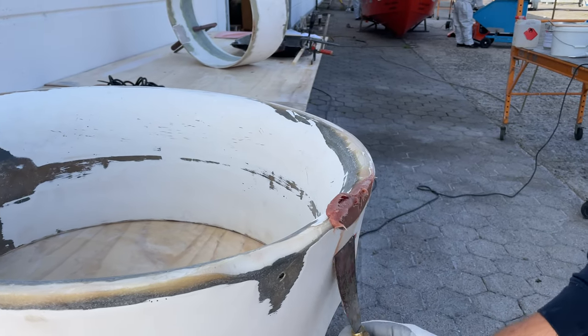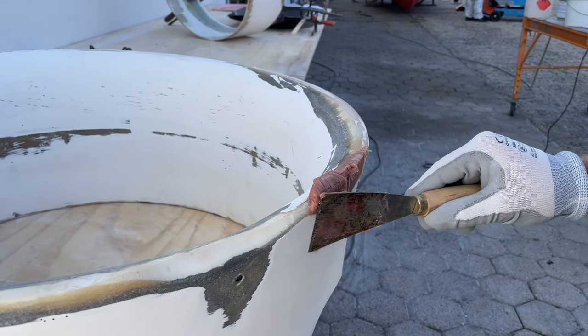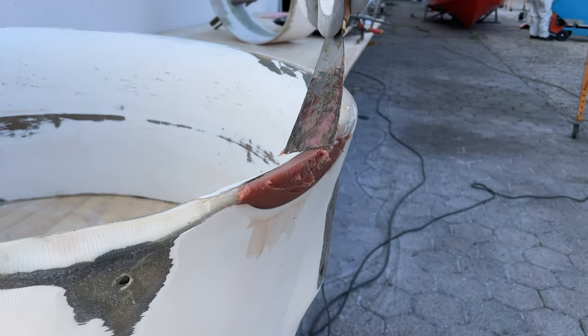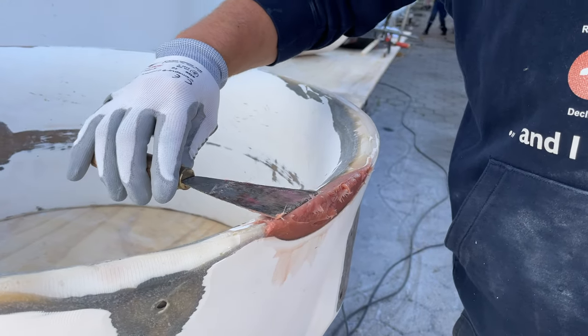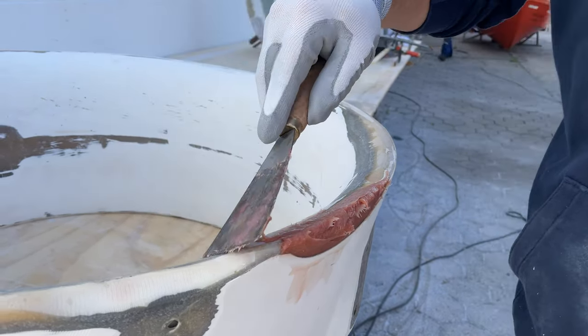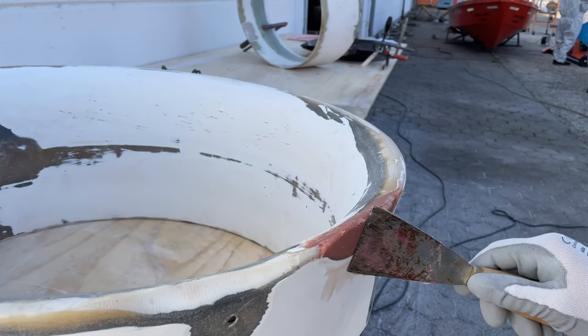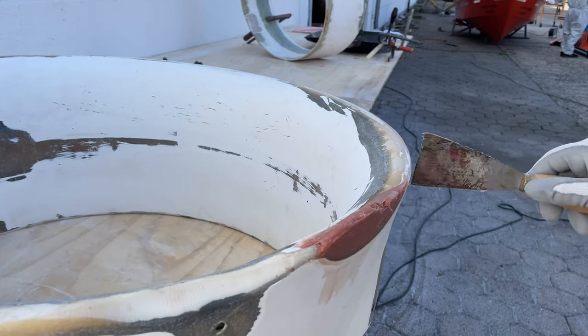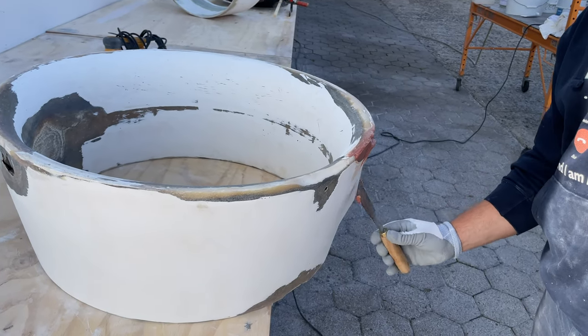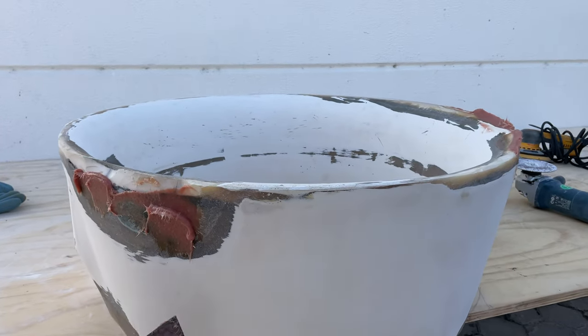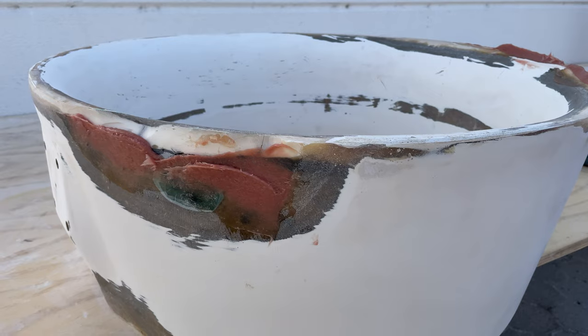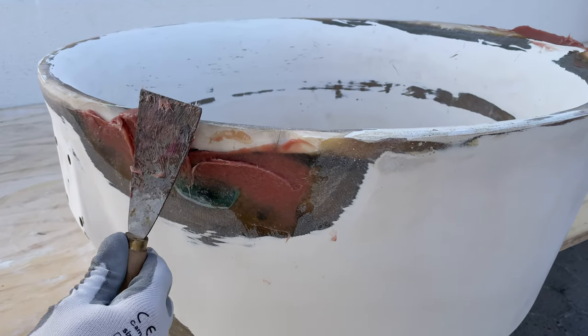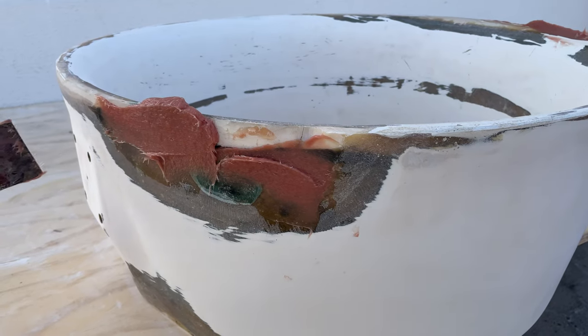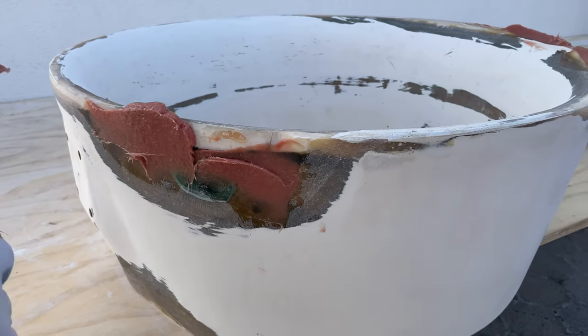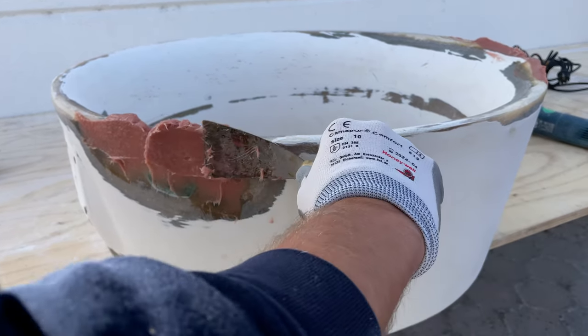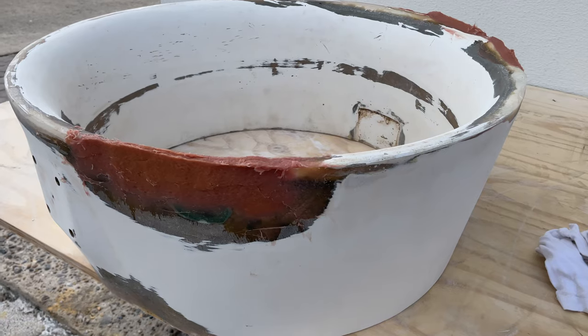So what we started out with was filling it with this fiber filler, or polyester resin with fibers in it, to try to match the contour of the original nozzle in the places where we had to completely grind it down. While this stuff is more structurally stable than a typical base filler, you don't want this to be on the outside of your part in the end. So if you hit it, it will just split off. That being said, you need some contour to laminate the fiberglass on top of. Therefore, we're filling everything so that we have something to work with, and we have a surface that after sanding is flat to then laminate on.